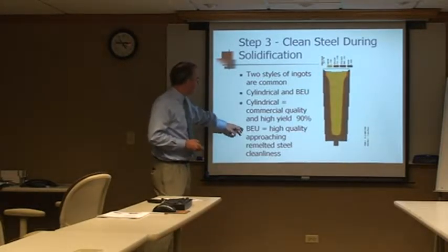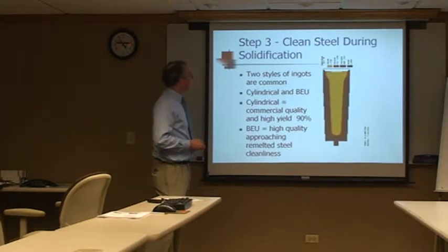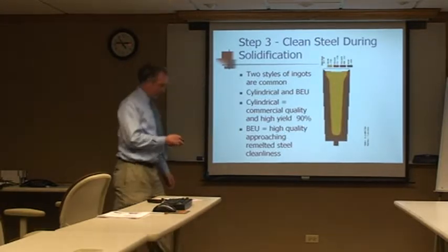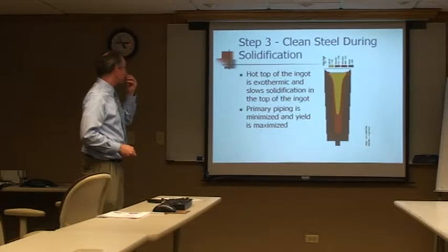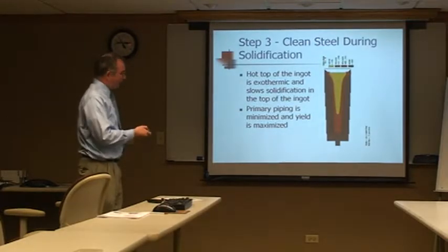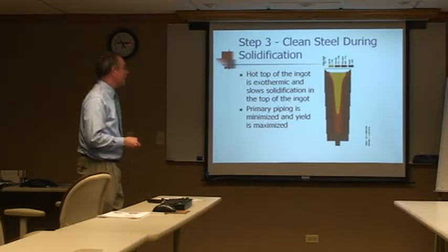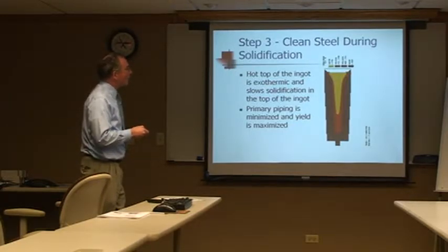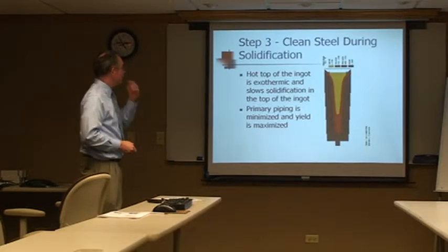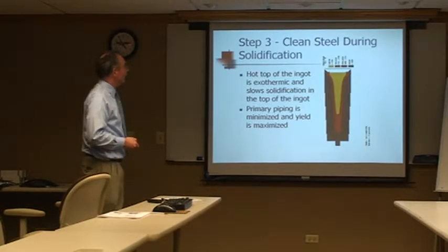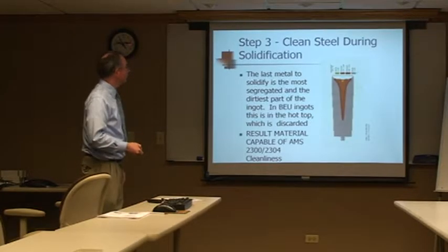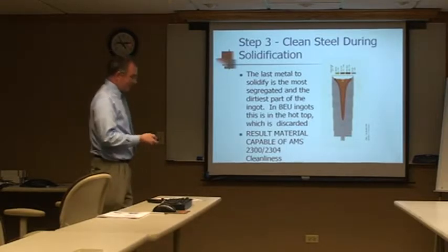With the big end up ingot, I'll come back to that in a second. Here we are back, talking a little bit more. Here we see the ingot at about 135 minutes, and you can see this hot top here being delayed. Solidification is progressing. And then finally, here's our tapered ingot.